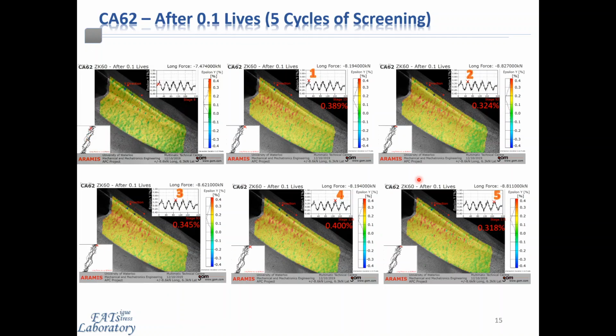Now looking at each of those 5 cycles in more detail, we can freeze frame the images at peak tension for each of those cycles observed, and we can see that the peak strains that are observed are very similar in each of the 5 cycles, but not completely identical. As the test progresses, we can see 0.389%, 0.324%, 0.345%. The reason for this is that it's a component level test that is load controlled in nature, and we're observing the strain response of the surface due to the applied loading at a much finer scale than the component level. Hence, the variations in each of the strains being observed here, because we're not controlling the strain, we're controlling the applied load.